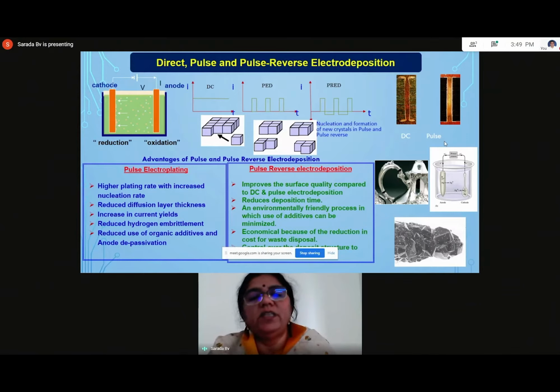Another advantage with electrodeposition is you can see this silver kettle over here. This is plated with silver by using electrodeposition. The most advantageous part of this electrodeposition is that it consists of so many curves, but still the uniformity is very much well maintained during the electrodeposition. That is what is required for deposition on porous materials, especially the porous carbon, which is the substrate for both anode and